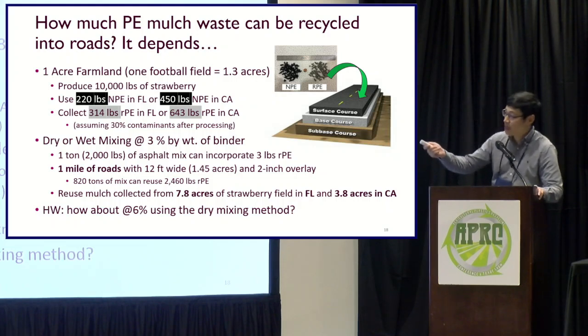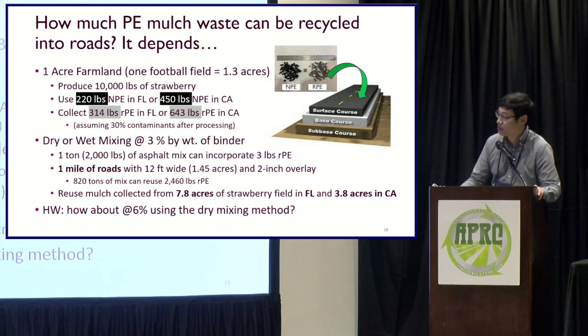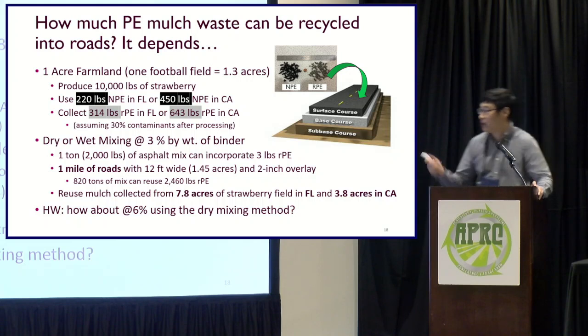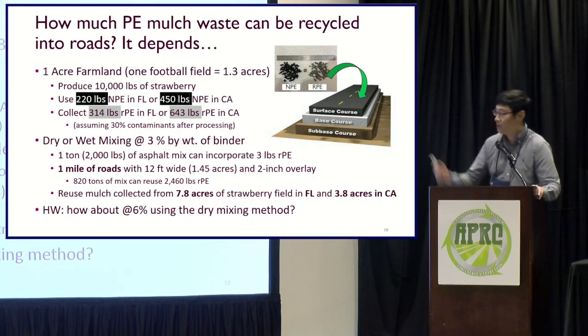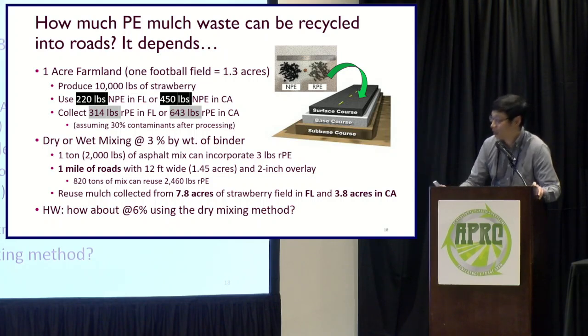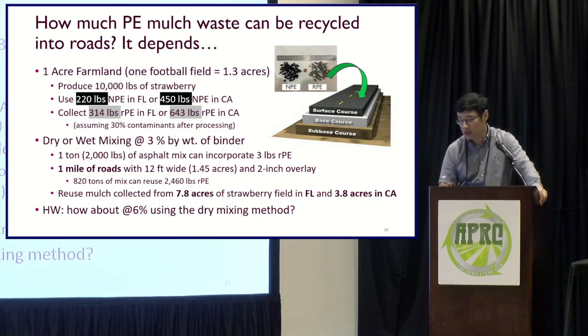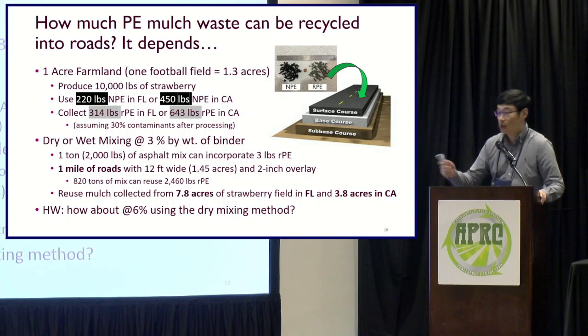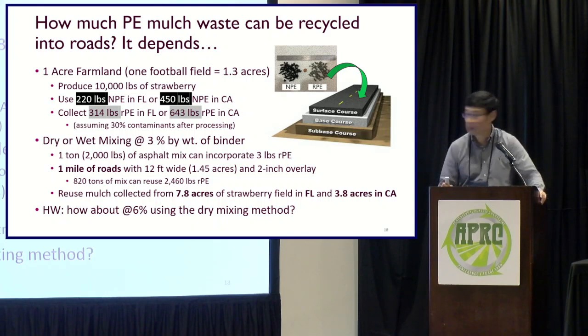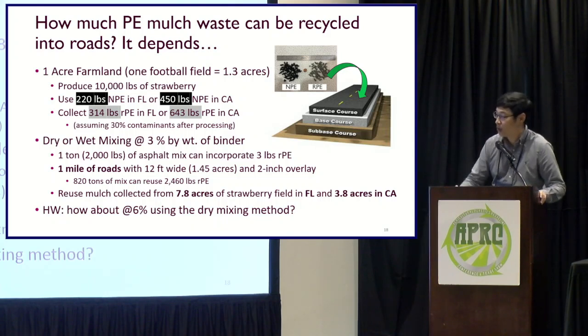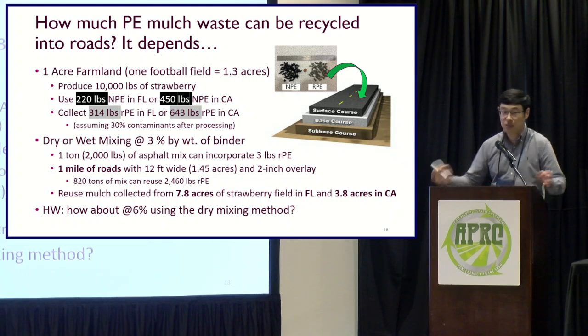And if we do the math, with dry or wet mixing at 3% by weight of the binder, for 1 ton of the mix we can incorporate 3 pounds of the recycled PE pellets. Well, when we build 1 mile of road with a thickness of 2 inches, roughly we have to use 820 tons of the mix and reuse around 2,500 pounds. It's a little bit over 1 ton of the RPE in this 1 mile of road.